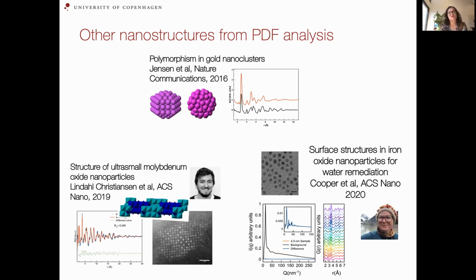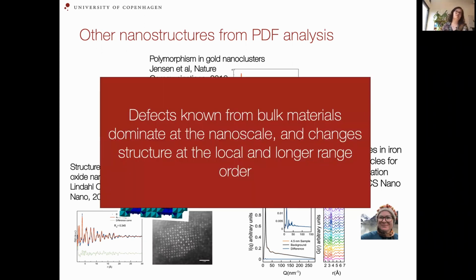And we've done this on quite a few different kinds of materials. I won't go through more of the examples here, but the main thing that we're learning is that when we go to the nanoscale, defects that are actually well known from bulk materials completely dominate and take over what then turns into the average or medium range structure in the nanomaterials. And that gives us some insight into how we can design materials, or what structures we can expect when we synthesize very small nanoparticles and get these size-dependent materials.